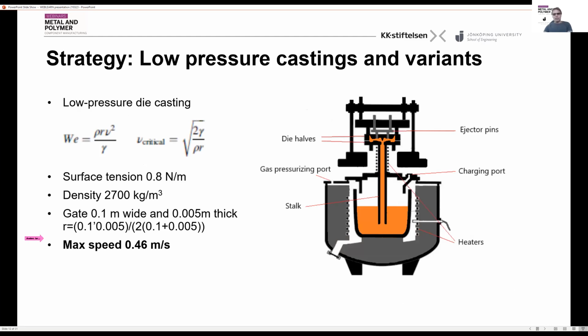One of the most standard processes that we have for high quality castings is low pressure die casting. In low pressure die casting, you have a furnace compartment, which is hermetically sealed, and you increase the gas pressure. That means that you force up the melt through the stalk into the die cavity here. Looking at this, in order not to have a turbulent fill, you can calculate a critical speed using the Weber number, and you end up with about half a meter per second as your fill speed. For low productivity processes and short fill lengths, this would be quite sufficient. But when we're talking about casting a quarter of a car, you need much higher speeds in order to do that. So we can take the next.